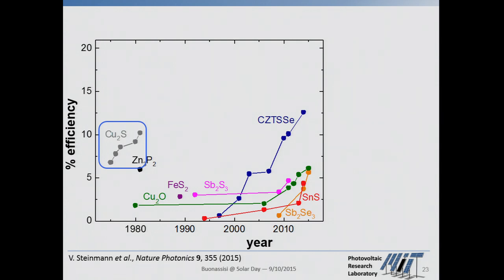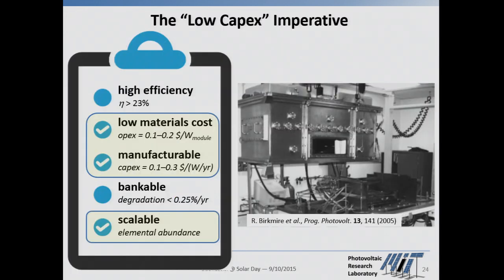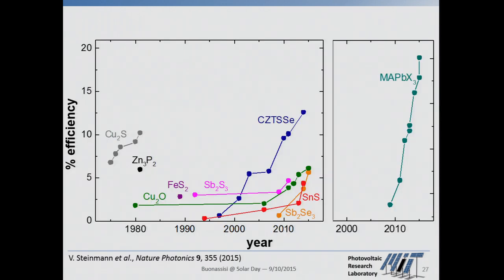And what killed cuprous sulfide was the instability. We wanted a bankable material with a degradation rate of less than 0.25% per year, but in fact it was not bankable. The degradation rate was within days. The devices exhibited hysteresis and eventually failed critically. And interestingly, as history tends to repeat itself, there is a new material on the scene, methyl ammonium lead halide, or more generally, organic lead halide perovskites.